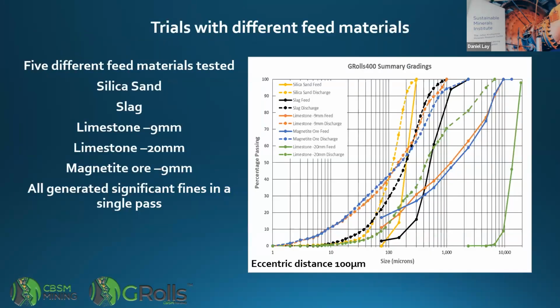We've done trials on a whole lot of different feed materials. We would like to trial more feed materials, but so far this is limestone, silica sand, a slag material, and then a magnetite ore. And they all generate quite high percentages at the 100 micron grading size, 20 to 40%.